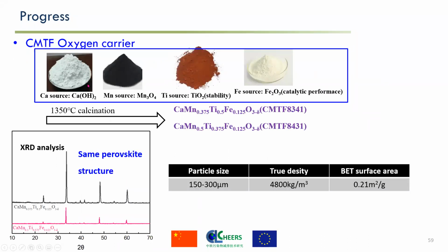Based on the above performance, SINTEF developed some CMTF oxygen carriers and sent two of them to Tsinghua University for research. This material consists of calcium, manganese, titanium, and iron. You can see all the elements and raw materials are very cheap and low toxic. After calcination at 1350 degrees, a perovskite structure formed in the material, and the two oxygen carriers have a similar perovskite structure. The particle size, true density, and BET surface area are listed in this table.